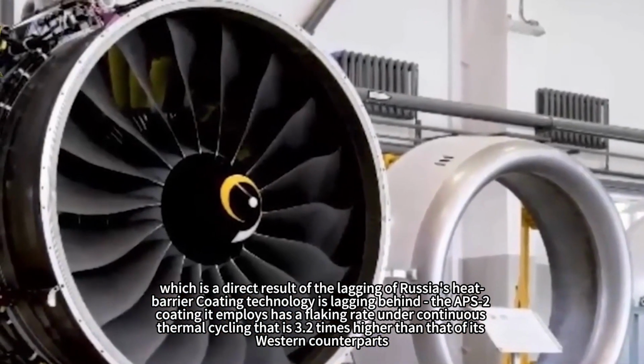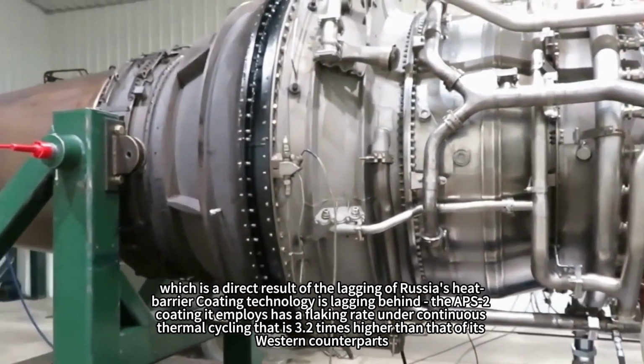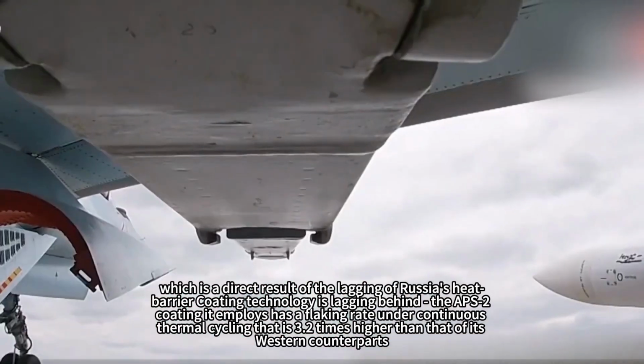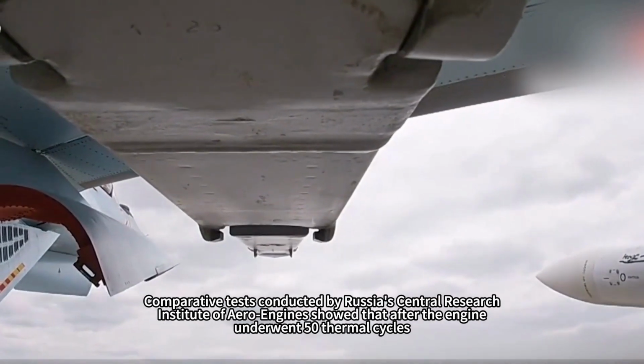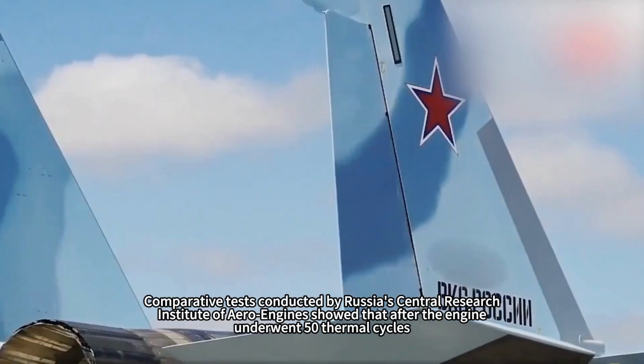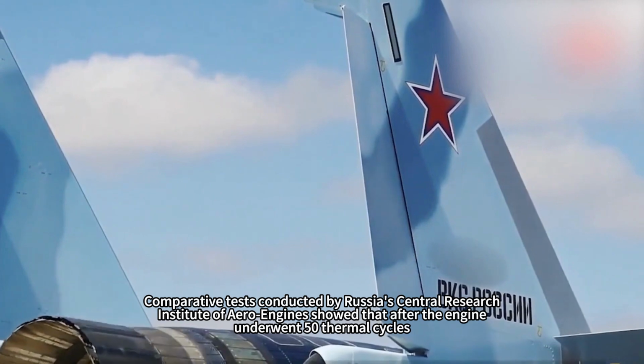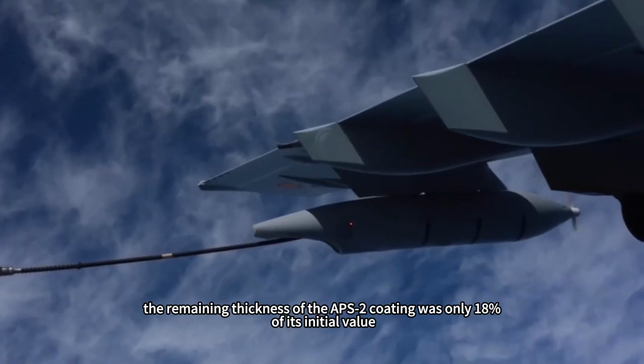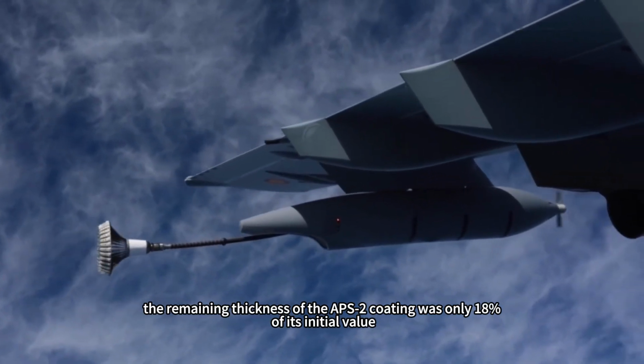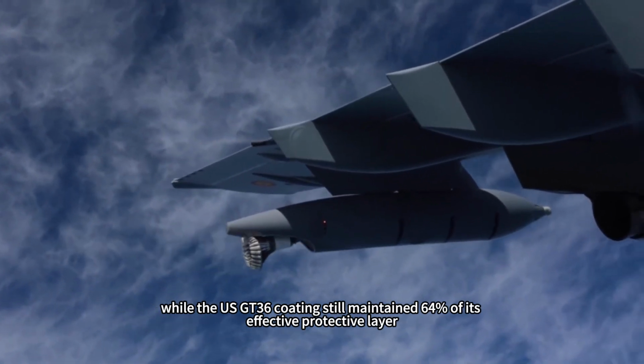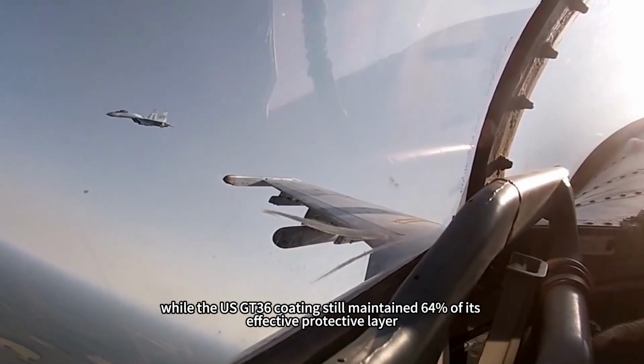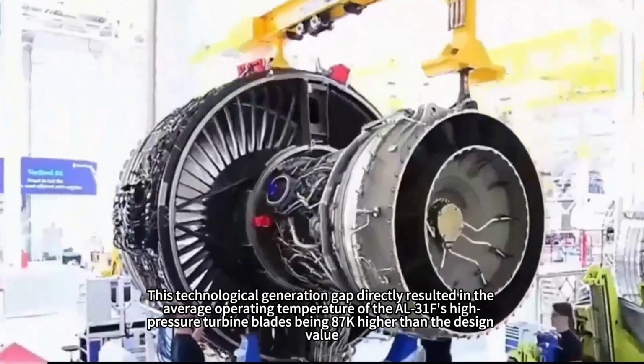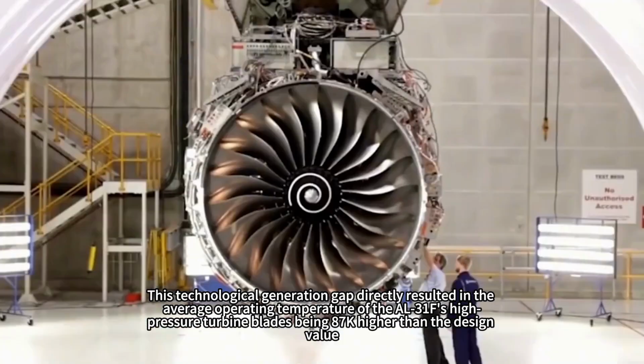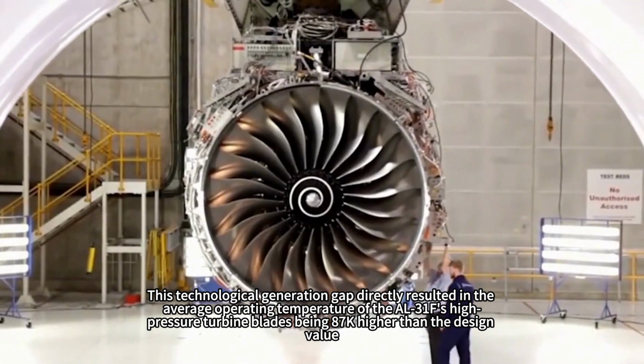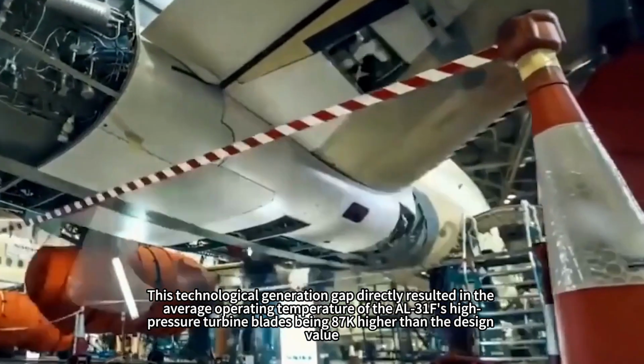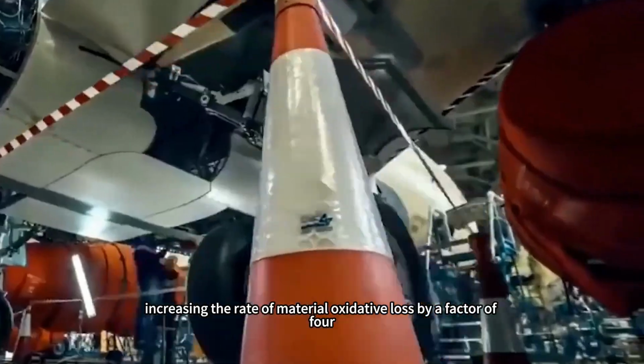The APS-2 coating it employs has a flaking rate under continuous thermal cycling that is 3.2 times higher than that of its Western counterparts. Comparative tests conducted by Russia's Central Research Institute of Aero-Engines showed that after the engine underwent 50 thermal cycles, the remaining thickness of the APS-2 coating was only 18% of its initial value, while the USGT-36 coating still maintained 64% of its effective protective layer. This technological generation gap directly resulted in the average operating temperature of the AL-31F's high-pressure turbine blades being 87K higher than the design value, increasing the rate of material oxidative loss by a factor of 4.